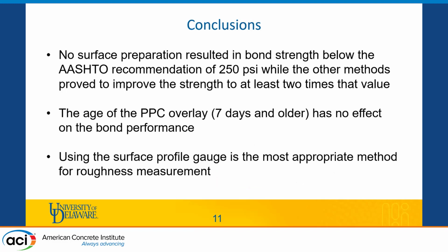As a conclusion, we can say that no surface preparation resulted in bond strength below the AASHTO recommendation of 250 psi, while the other methods proved to improve the strength to at least 2 times that value. We can also say that the age of PPC overlay, 7 days or older, has no effect on the bond performance. And finally, we can say that using the surface profile gauge is the most appropriate method for the roughness measurement due to having difficulties of using the other two.